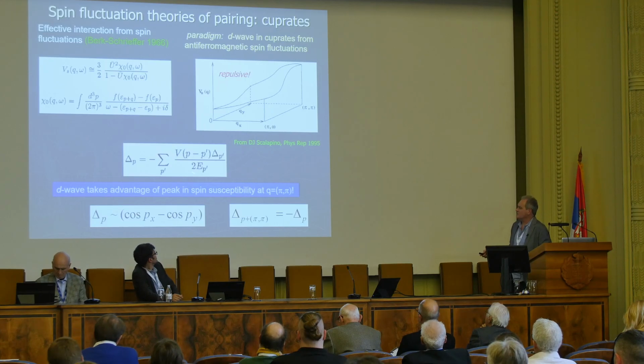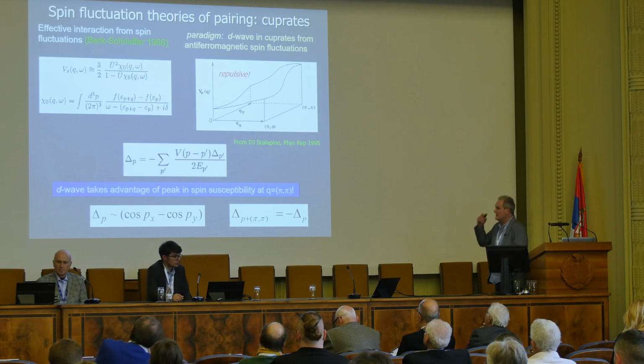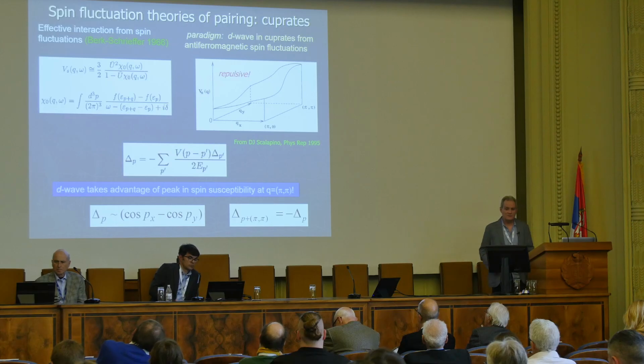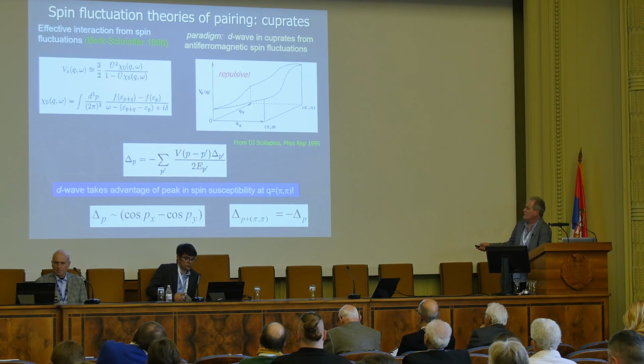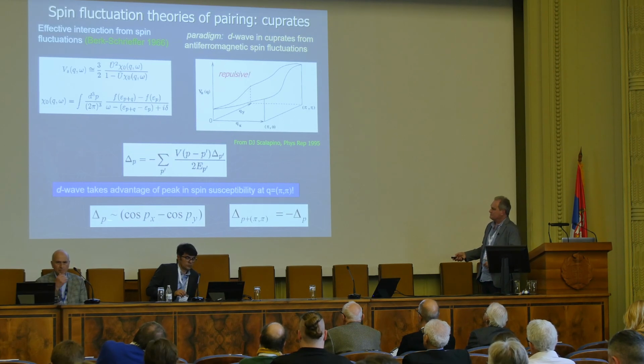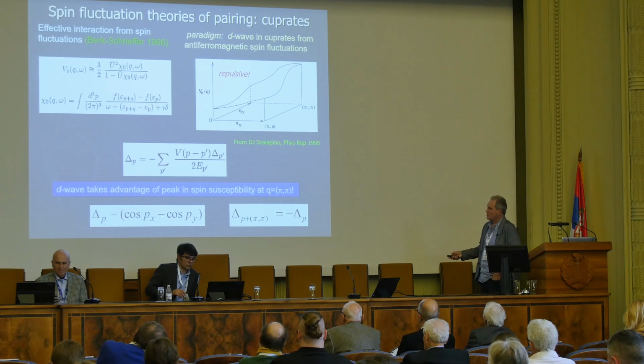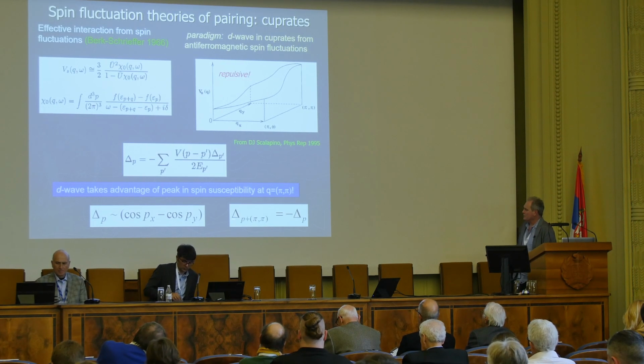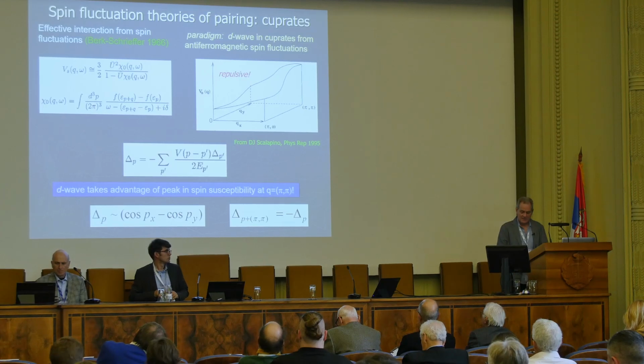Everything on the right-hand side is positive except for this minus sign, so I can't get a solution that way. What I have to do is allow the order parameter to change sign as I go over the Fermi surface as a function of momentum. And this particular function, cosine px minus cosine py, has just the right properties that when I shift by (pi, pi), 0 to (pi, pi), I get a minus sign to take advantage of this peak.